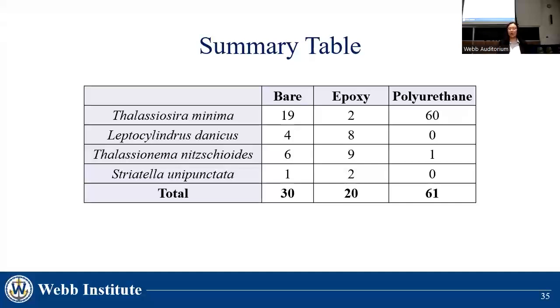Factors to consider while evaluating the trends of this data include the limited testing window, potential interactions due to the proximity of copper-based biocidal paint, and data collection methodology. As only limited points could be reasonably tested in this fashion, data can be more strongly relied on to provide an indication of growth types than serve as representative samples of the total population.